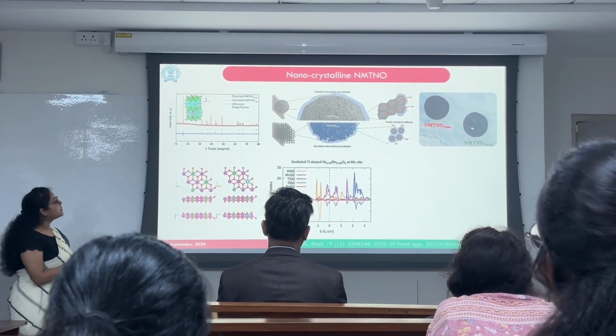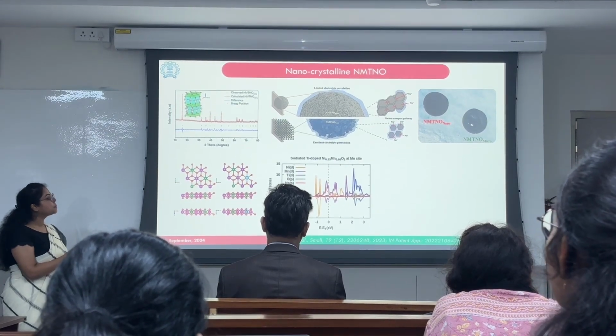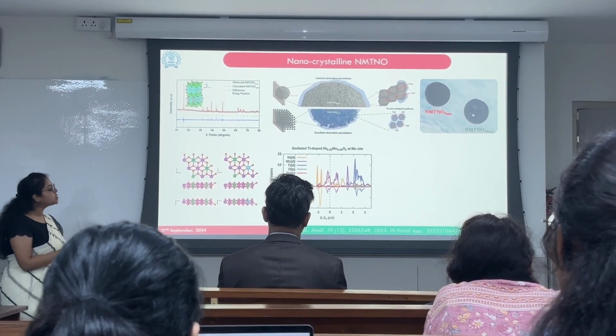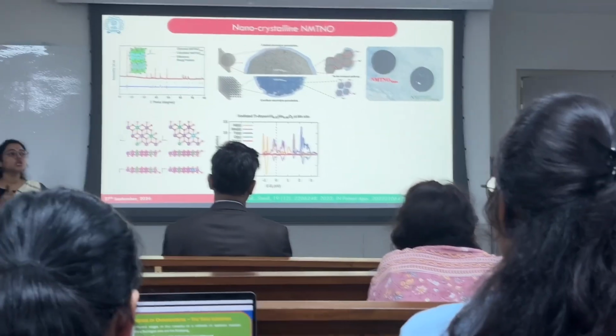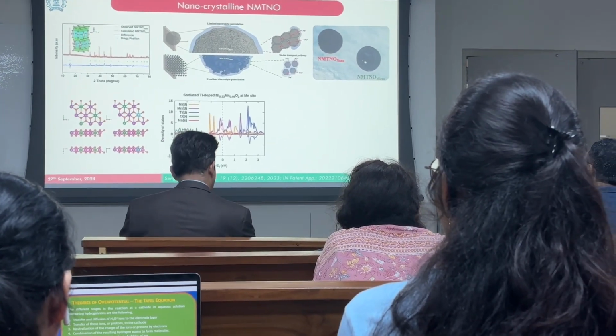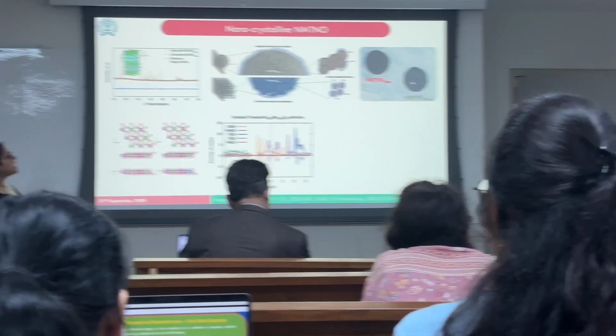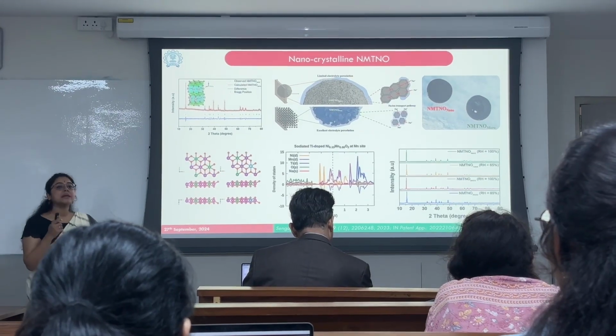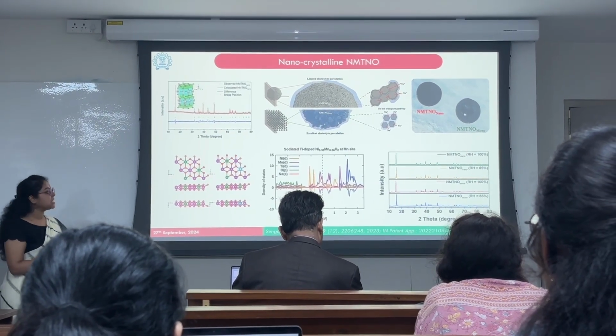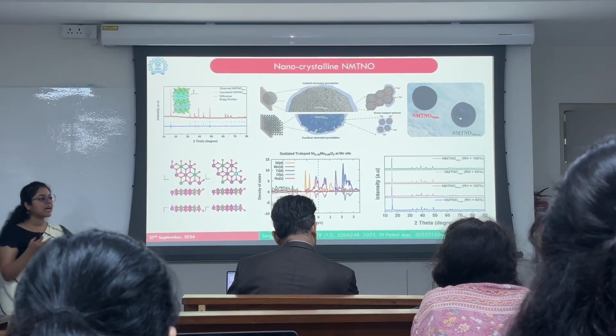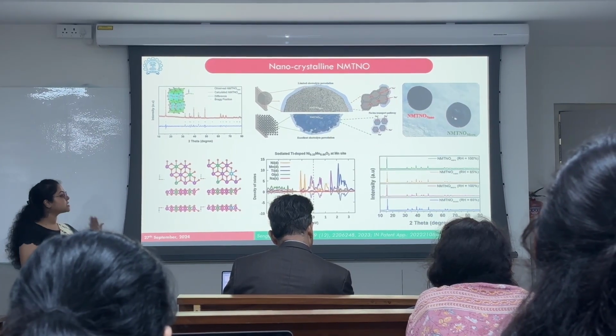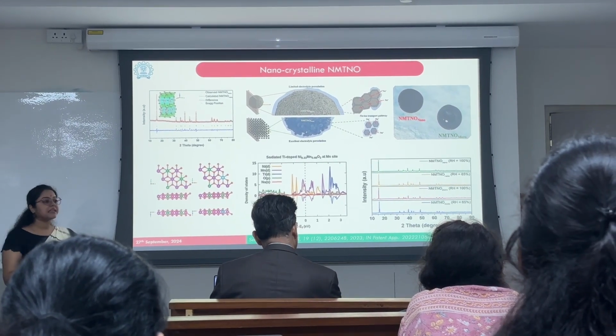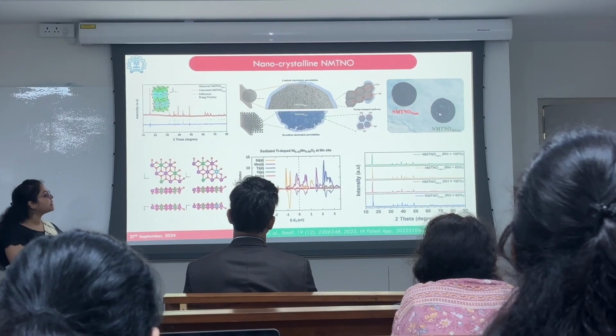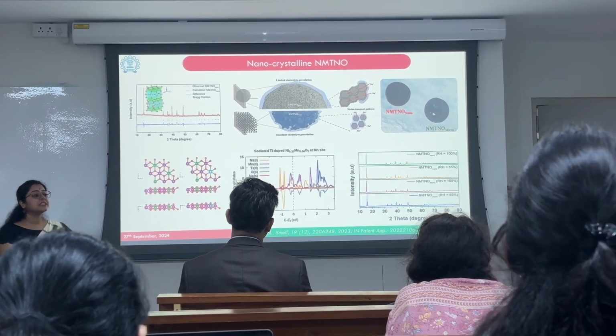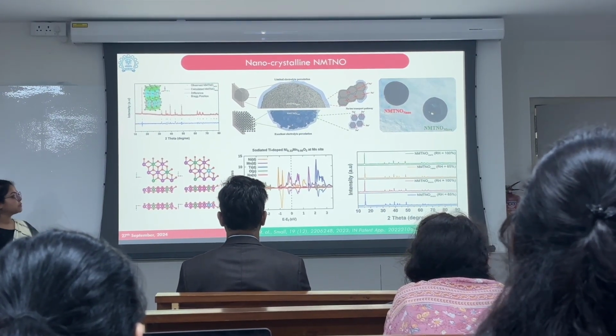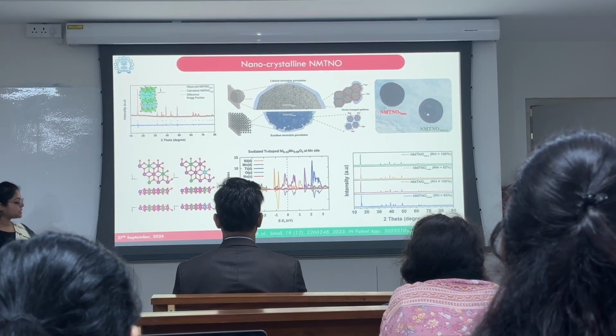We further confirmed the position of titanium doping through DFT analysis with the help of Dr. Gayatri Barik, and we saw that the titanium is doped at the manganese site, and through the PDOS calculation we observed that doping titanium has also enhanced the electrical conductivity. And finally, we also validated the air moisture stability through the XRD refinement. We had taken the as-synthesized powder, exposed it in air and immersed it in water, and finally acquired the X-ray diffraction, which shows that the majority of the bulk structure remains constant.